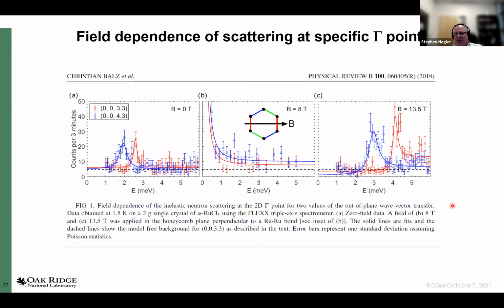Do we see that? Well, here's a measurement that goes higher in field in neutron scattering. This is a triple axis measurement done at FLEXX, for those who are familiar with it, in Germany. And now we're looking at two different gamma points in 2 dimensions, but different wave vectors in 3 dimensions, right? And again, this is at low temperature in the ordered state. It is a 3-dimensional system.